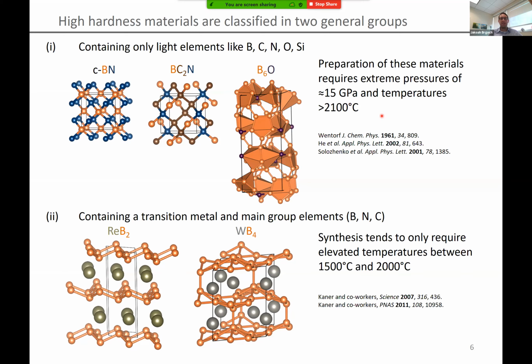The excitement of these phases stems from the fact that the synthesis of these borides only requires elevated temperatures, like 1500 or 2000 degrees Celsius. Now, my colleagues in organic chemistry tend to laugh when I talk about doing synthesis at 1500 degrees Celsius - this is a ridiculous temperature for organic chemistry. But from a materials chemistry perspective, 1500, 2000 degrees Celsius is really not that crazy.